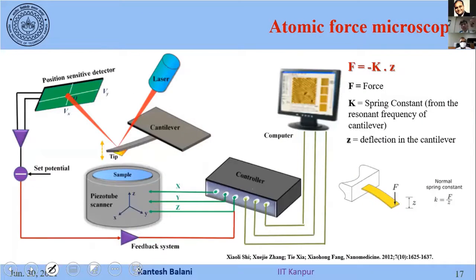Right. So here we have used AFM, and in AFM we see that force equals minus K into Z, where K is the spring constant and Z is the deflection. We would like to have the maximum deflection. So intuitively we think we should keep K as low as possible, so that I can have a very high deflection. But that is not so good, because if I keep the spring constant very low, then even thermal fluctuations at room temperature will start giving some signals. That will mean higher background, which I do not want. So typically K is taken as 1 Newton per meter or so.